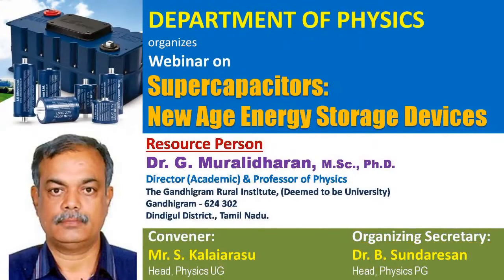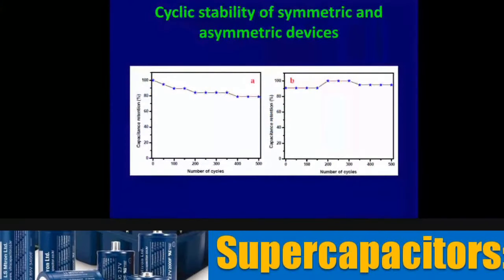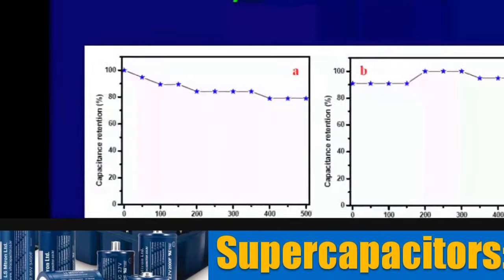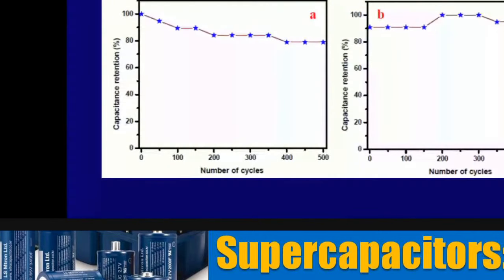The most important question is cycling stability. The cyclic stability is the most important aspect. You can see the pictures, you see that the cyclic stability is this. We start with 100%, but at 500 cycles you see that it goes to 80%. It is for some other material, and you see that this has to be arrested.